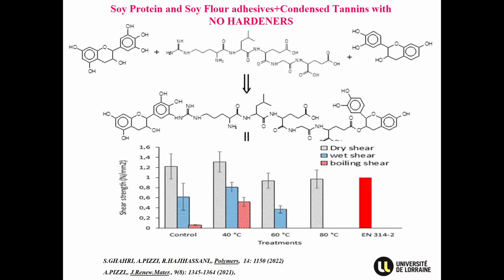We found, for instance, that soy protein and soy flour condensed with tannins with no hardener. The reaction happened at 40 degrees centigrade. So what you have to do is to have a fraction of a protein that reacted with a flavonoid tannin at 40 degrees centigrade, not to cross-link it completely, and then used for plywood. You can see here the results: the dry shear strength, the wet shear strength, the boiled shear strength. When the reaction is done at 40 degrees centigrade, you get these results once you press the plywood at the normal pressure you want. What it means is that if you increase the temperature, you will have nothing anymore because it started to cross-link. That means you can press boards at a temperature that is lower than what you press at today. You get no aldehydes whatsoever, just the protein and the tannin. It works very well and is very, very easy to use.